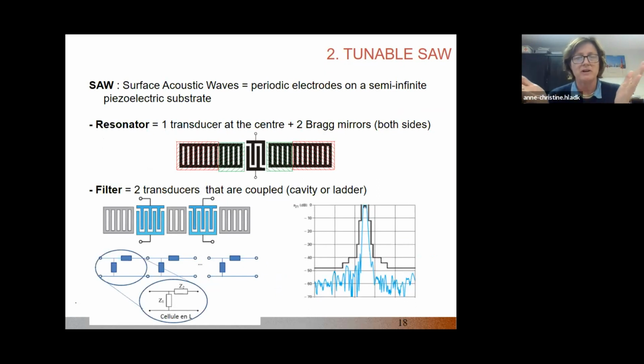For surface acoustic waves, you consider a semi-infinite piezoelectric substrate. You put electrodes on the top at the surface, periodic electrodes, interdigitated electrodes. So it means that on one part you have +1 volt, on the other one you have -1 volt. Then when you apply this voltage, there is a deformation at the surface of the piezoelectric, and then a wave will propagate on the substrate. Okay, so now this is SAW.